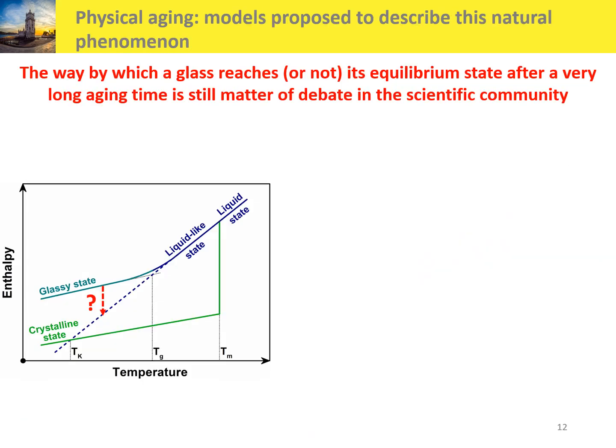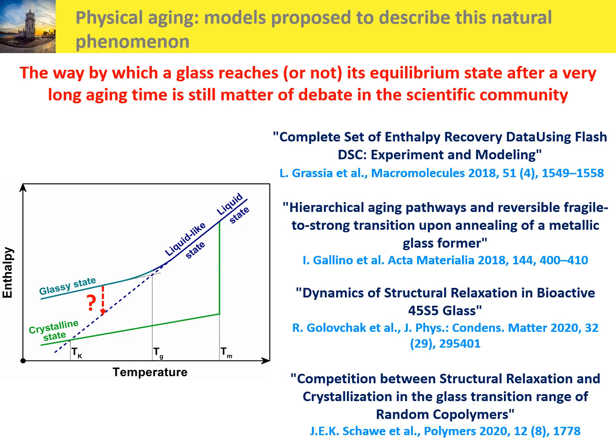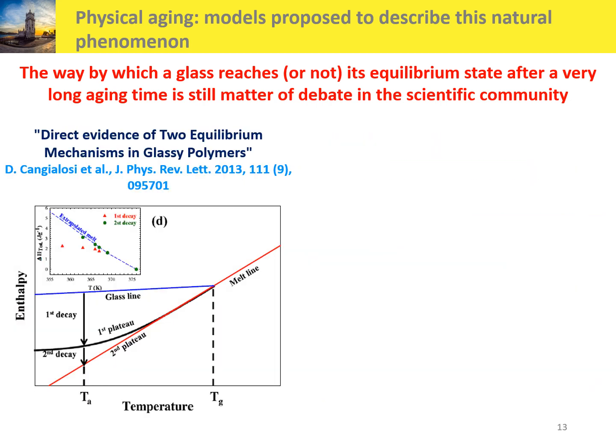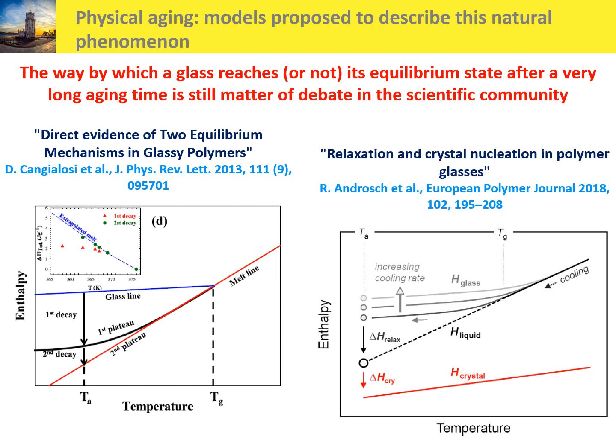But the way by which a glass reaches or not its equilibrium state after a very long aging time is still a matter of debate in the scientific community. I can, for example, mention these very recent papers from 2018 up to 2020 about these topics. More particularly, I would like to mention the work of Daniele Cangialosi, published in Physical Review Letters, which evidenced 2 equilibrium mechanisms during the physical aging, by highlighting an intermediate plateau here. I would like also to mention this recent paper of René Androsch, which explains, in fact, the possibility to crystallize after the physical aging if the time is long enough.